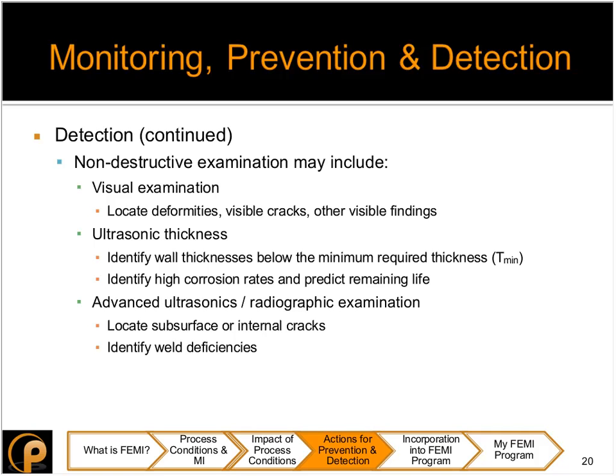A more advanced technique is ultrasonic thickness readings, which will help you to re-evaluate your equipment based upon your thickness, about whether you should derate your equipment or whether it's good for whatever remaining life that you have. Another thing is taking thickness readings can give you corrosion rates, and corrosion rates will determine when you want to do your next inspection and what frequency of inspection you should have.